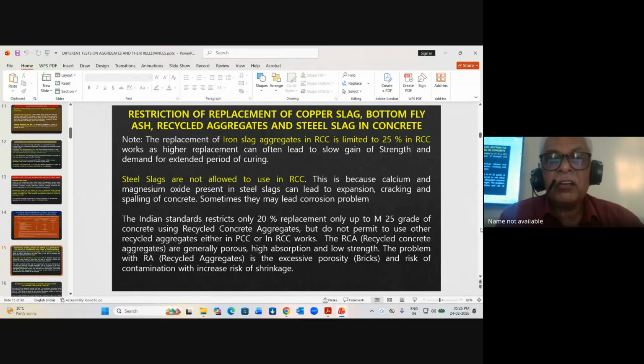Steel slags are not allowed to use in concrete in RCC work as per this table. This is because calcium and magnesium oxide present in the steel slags can lead to expansion, cracking, and spalling of concrete. Sometimes they may even lead to corrosion problems. So these are the disadvantages with respect to steel slag.